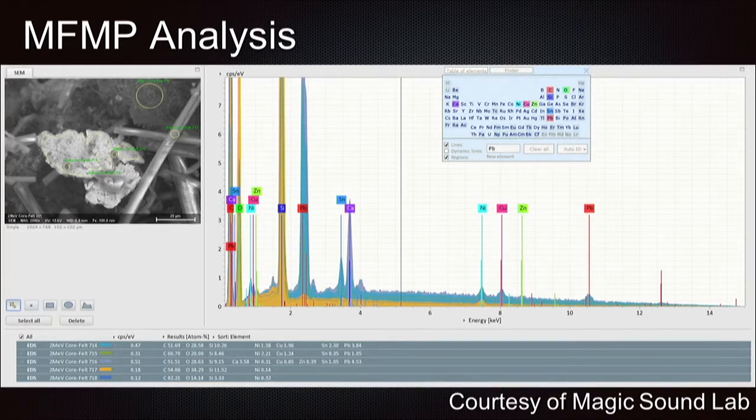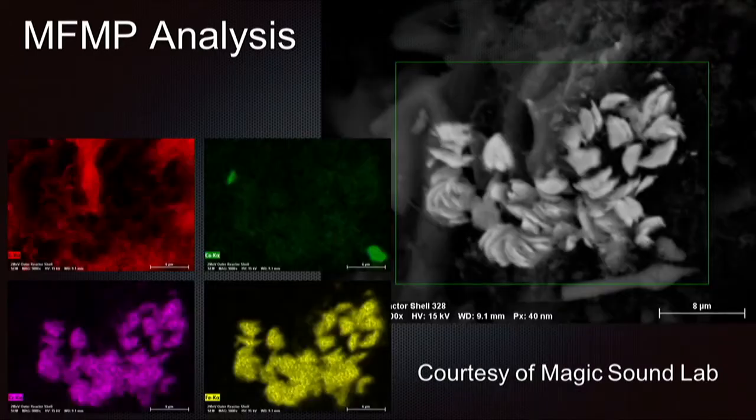Firstly, we found these fibers of carbon and also fluffy carbon. And so we're actually looking into some things that came out of the core, and also a big blob here. And in this blob, we found nickel, copper, tin, and lead. Obviously, we're going to see nickel. The interesting thing is there was silicon in large abundance. Also, you see calcium here, and a lot of carbon. So where's that carbon coming from? We also found these platelets. So this is the fluffy type of carbon, and these platelets, and they had iron, chrome, and calcium in them.